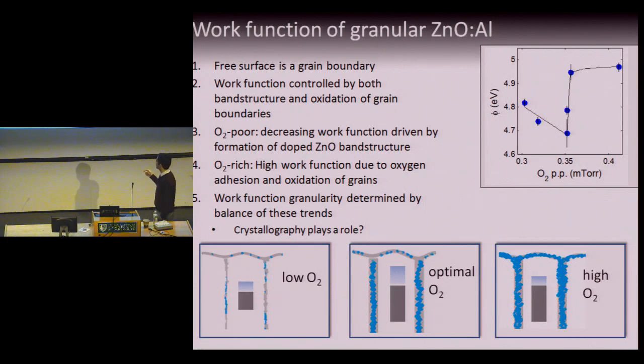Right at optimal, you have a situation where you have oxygen defects segregated along the grain boundaries. In the grains themselves, they're optimized, which actually tends to push their Fermi level up, push their work function down. So right here, you expect now the highest degree of contrast in work function on and off grain boundaries. So this is a model that actually not only explains the granularity, these pretty image pictures we saw of the work function on and off grain boundaries, it also explains the overall trend in work function.